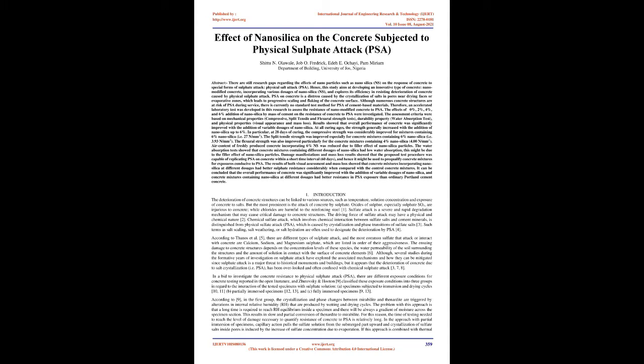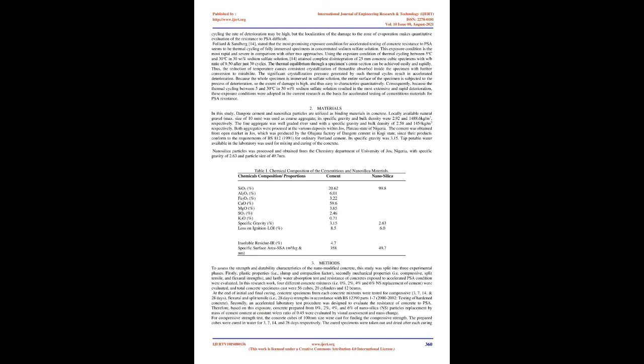It can be concluded that the overall performance of concrete was significantly improved with the addition of variable dosages of nano-silica, and concrete mixtures containing nano-silica at different dosages had better resistance in PSA exposure than ordinary Portland cement concrete. Introduction. The deterioration of concrete structures can be linked to various sources, such as temperature, solution concentration, and exposure of concrete to salts. But the most prominent is the attack of concrete by sulfate.